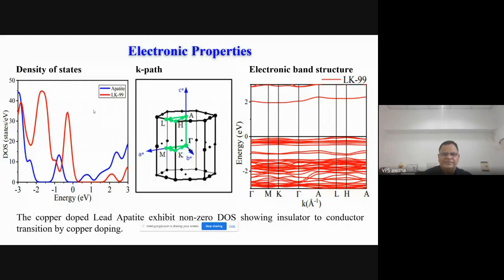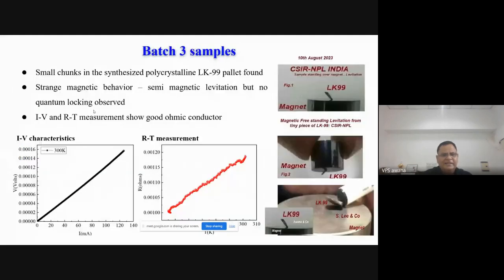There were some assumptions, the DOS plus RVB and all that combination, strong correlations, and some papers came, I will come to that. So until now, this was our good story, that we could get a good sample, and even that sample is also not superconducting. Then in this batch, the same sample, in fact, if you measure its resistivity from 300 Kelvin down to around 240 Kelvin, it's metallic, but there is no sign of transition and all that. In fact, their transition is well above room temperature.